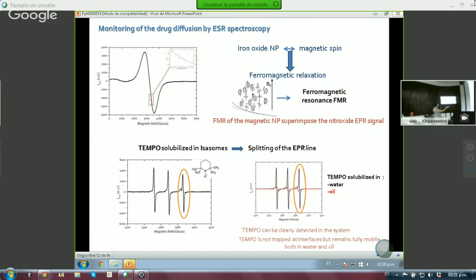If you look at the one on the left-hand side, you have the spectra, the intensity as a function of the magnetic field. And the one which is highlighted, this is the effect of the tempo, and you can see that we can see a difference in it. In the next one on the right-hand side, you have two different results. One is when we had the tempo solubilized in water, in blue, and in oil. And what we can see is really that it doesn't make any difference if we use the water or the oil to solubilize the tempo, and the tempo is the drug which is being used.